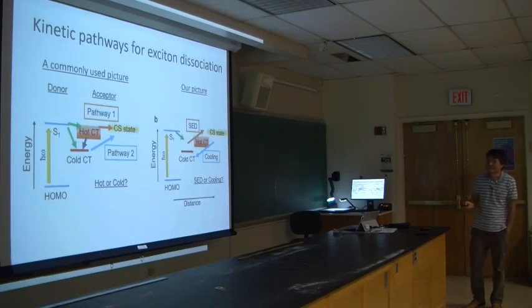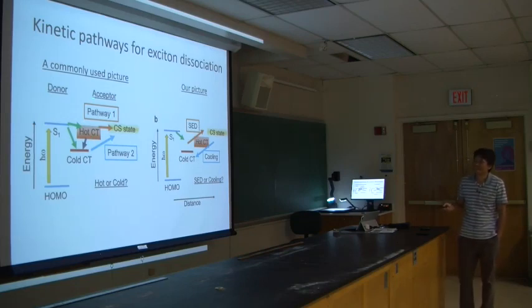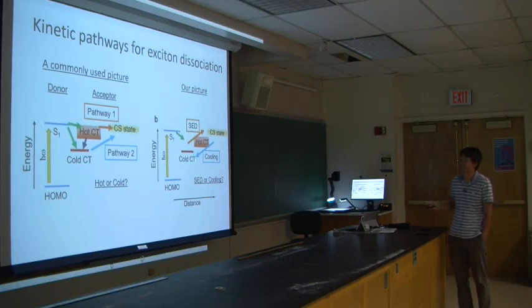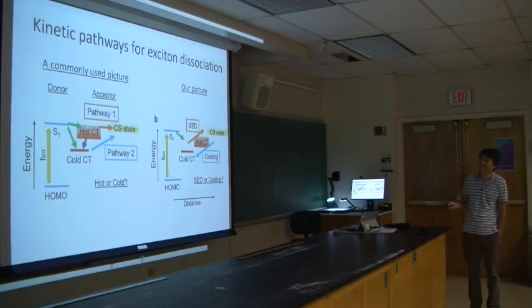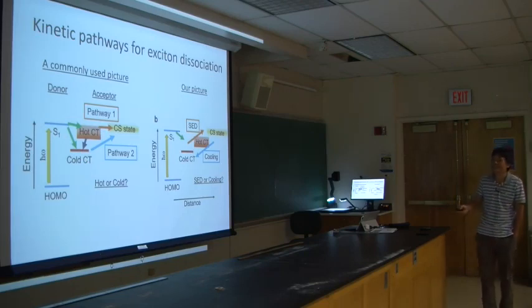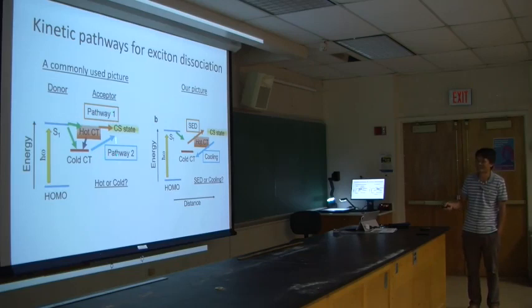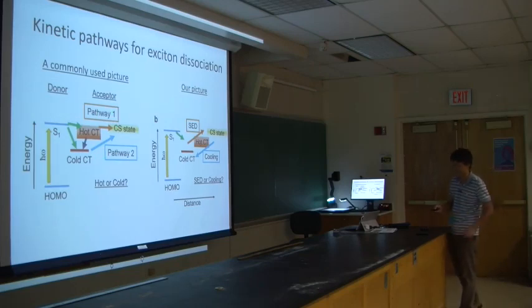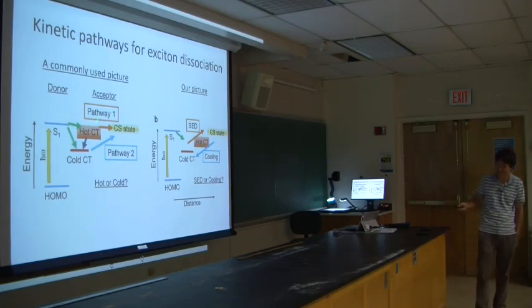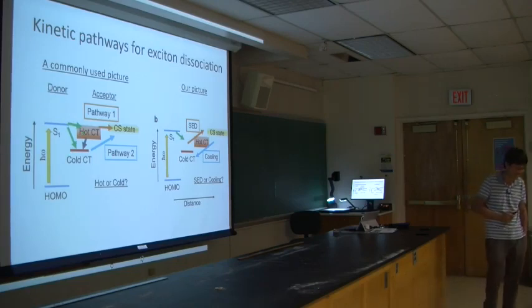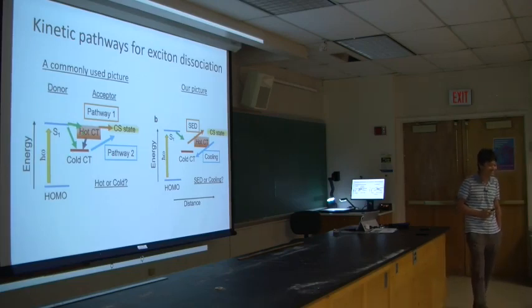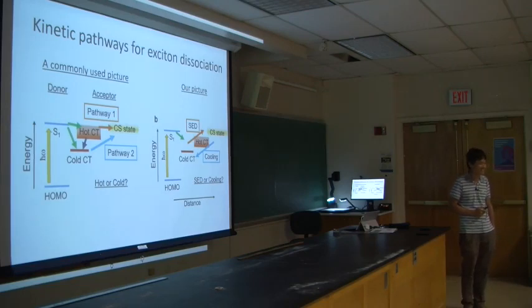So here I'd just like to talk about how people have commonly thought about this over the last decade and what we think is different in our current picture. Usually people think you populate these hot CT states, but these hot CT states always relax to the cold CT state on a very fast time scale. Therefore they always look at the competition between these different pathways: the separation of the hot CT exciton and the separation of the cold CT exciton. We think that picture is not quite right, and indeed it leads to many different arguments.